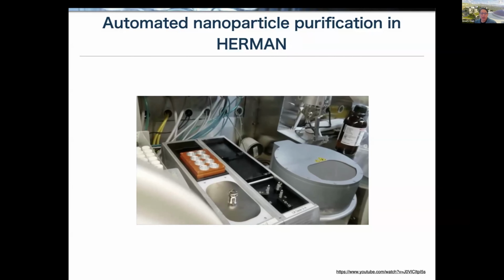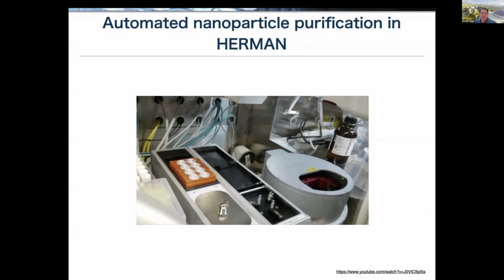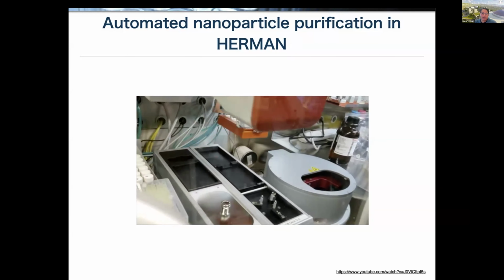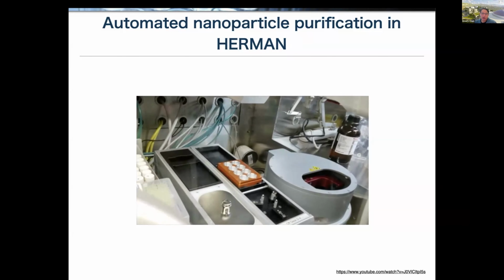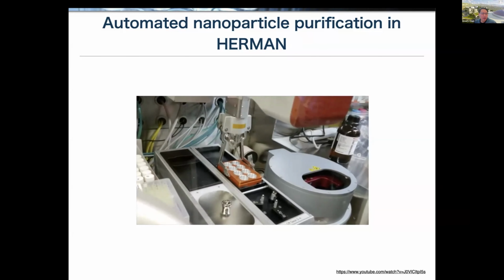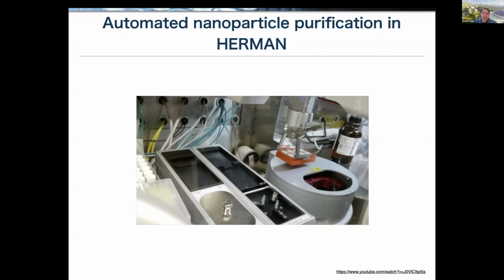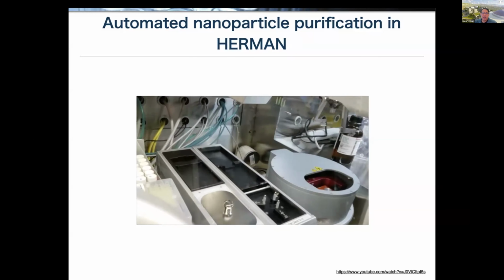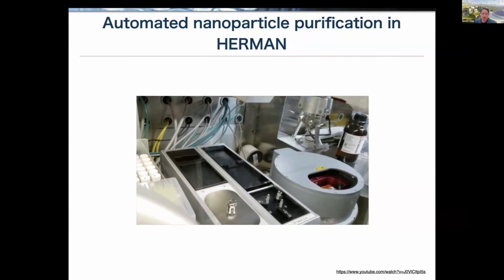But for other types of characterization like X-ray diffraction and TEM, you do have to purify the particles. And this is really difficult for most new users because it's not typically well described in the literature. And also it can depend a lot on the different particle sizes and particle types.